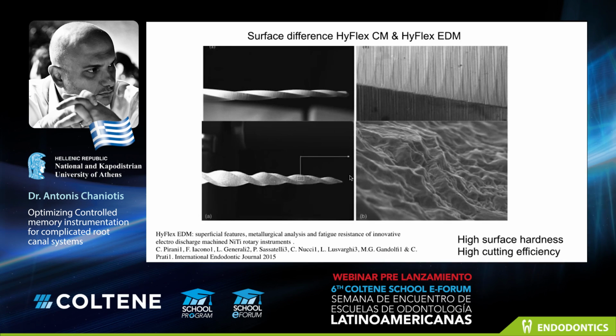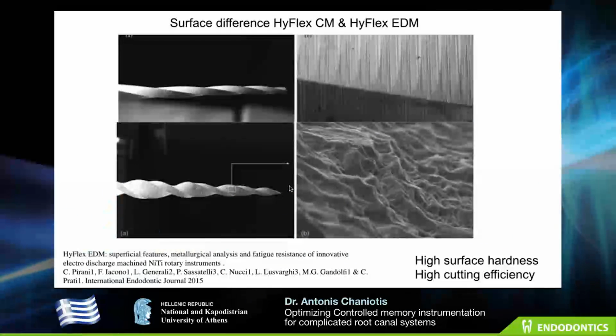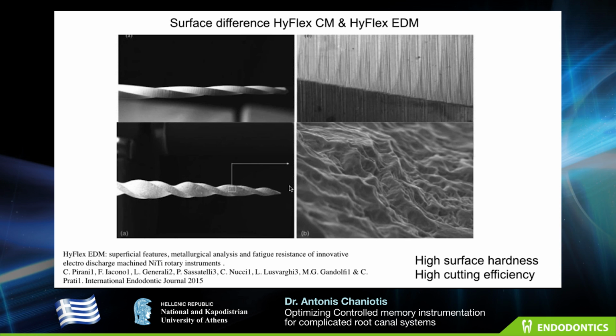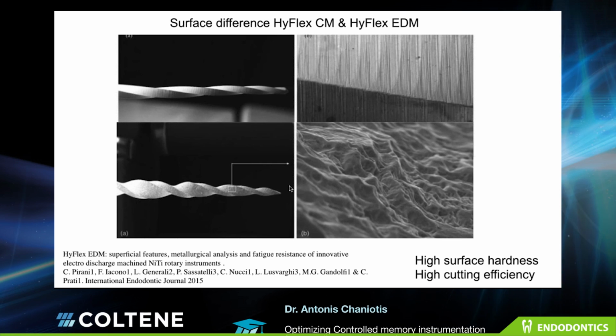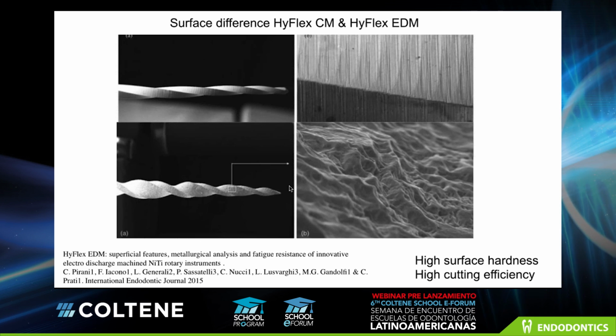Electrical discharge machining, you can see here the difference, under the scanning electron microscope, between the HyFlex CM and EDM. In the first row, it's the CM, and you can see the very smooth surface of the CM, and in the higher magnification the striations that come from the grinding wheel, because the HyFlex CM is ground. We make the flutes of HyFlex CM with a grinding wheel. On the contrary, the surface of the EDM looks like craters, because the EDM file is not ground. The flutes are made with electrical discharge machining with sparkles, so you can see these craters in the surface.